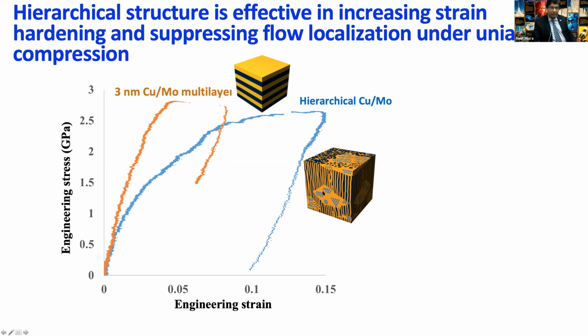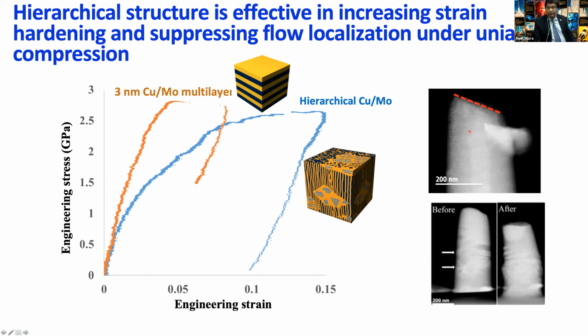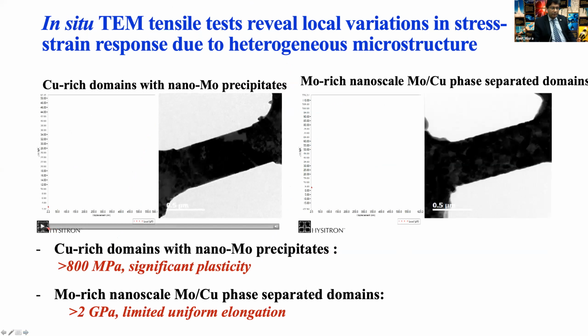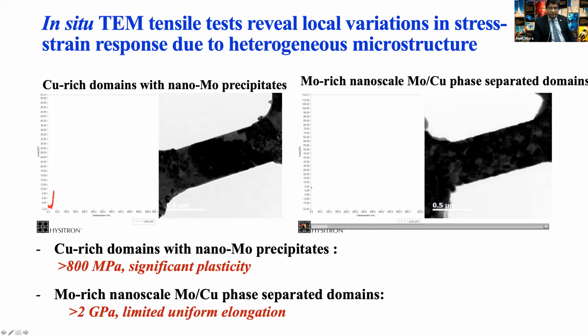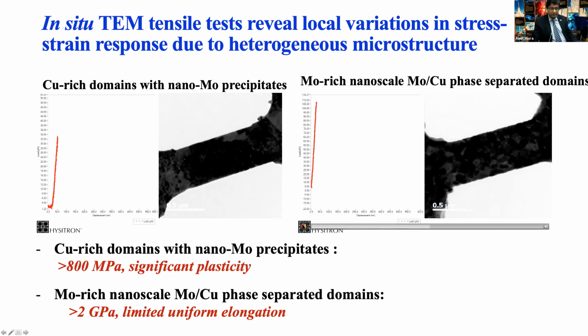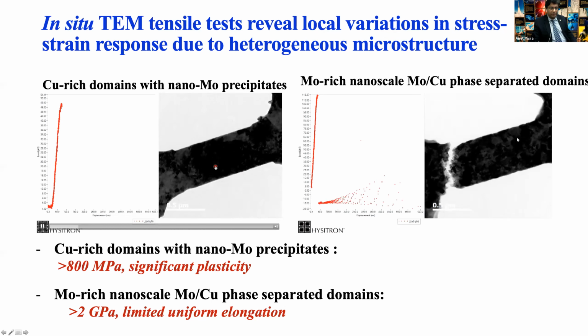So by getting a very high strain hardening rate, we are able to get uniform distribution in plasticity, from that shear localization to more uniform distribution in plasticity at small scale. We've also done tension tests. So we can do a FIB lift out and do a tension test inside a transmission electron microscope. So you can measure the stress strain response of the two different composites inside that hierarchical structure.